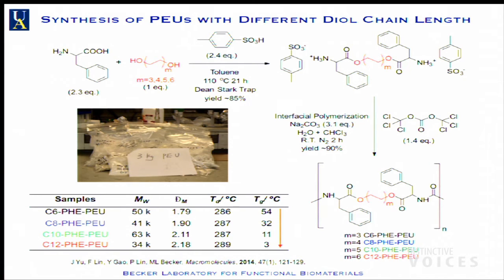But you can actually make this on a multi-kilogram scale on the benchtop, at sub-reflux temperatures with a Dean-Stark trap. This is the easiest organic chemistry experiment you'll ever do. You can recrystallize it in a bucket. You come back and you can use phosgene, which is a little more concerning, or triphosgene in this case, which is a solid, under basic conditions, again in a large pot, and you can make this amino acid-based polyester urea. In this case, it's phenylalanine, a benzyl aromatic amino acid, in multi-kilogram quantities. We've made batches as large as 10 kilograms in my lab.